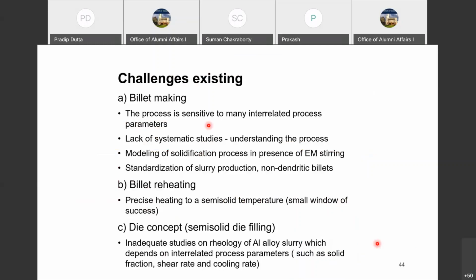Okay. But there are many challenges which are existing in this. The process is sensitive to many process parameters, then lack of understanding of the process, then modeling of the solidification process in presence of electromagnetic stirring. Standardization of slurry production is very difficult to achieve because there are too many variables, and material science is not an easy thing to tackle in terms of its behavior of materials at the elevated temperature and during solidification. Then billet reheating also, we need to precisely heat to a semi-solid temperature. So it's a very small window of success, within 2 or 3 degrees sometimes, that we need to heat something at a uniform temperature. And then finally, the die concept, semi-solid die filling and designing a die also we had done accordingly using CFD studies and experiments.